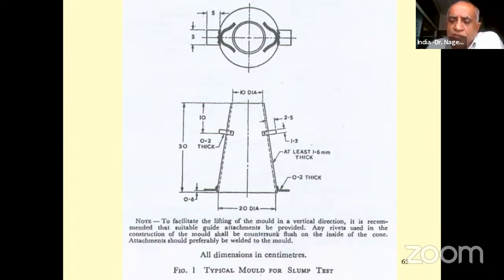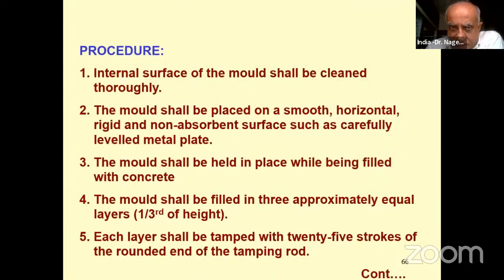So the slump cone is a very, very useful equipment to check the workability of concrete at sites as well as in the laboratory. Procedure. The internal surface of the mold shall be cleaned thoroughly. The mold shall be placed on a smooth, horizontal, rigid, and non-absorbent surface, such as a carefully leveled metal plate. The mold shall be held in place while being filled with concrete. The mold shall be filled in three approximately equal layers, and each layer shall be given 25 strokes with the rounded end of the tamping rod.